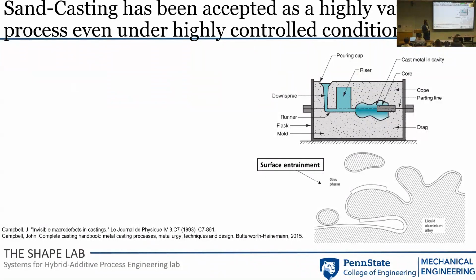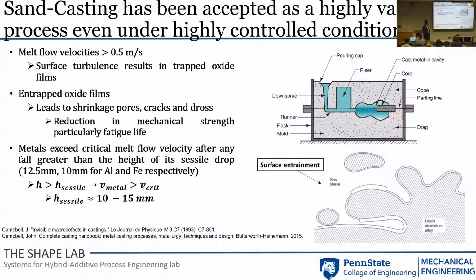But if you go down your pouring basin and you make a 90-degree turn, your potential energy to kinetic energy and your bend coefficient, what happens is you end up actually folding your oxides into your castings, like into your liquid metal, and you get a lot of gas trails and so forth. The good news is the literature is full of evidence that says if you're over 0.5 meter per second when you enter the mold, you're going to have surface turbulence and you're going to have trapped air and you're going to fold these oxides into like little pancakes.